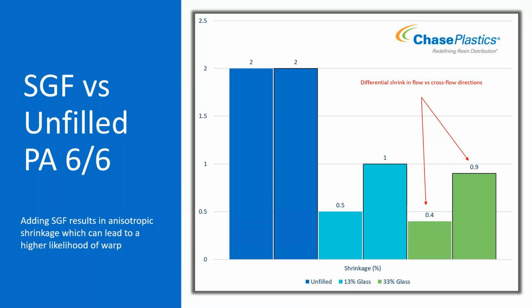You can see the 0.4 and the 0.5 - those are in your flow direction. It does not want to shrink nearly as much because of the glass getting in the way. In your cross flow direction you're looking at 1% versus 0.9%, or 10 versus 9 thou. So a big difference - you have double the shrinkage in the cross flow direction compared to the flow direction. This is non-uniform shrinkage, anisotropic shrink. That right there is what causes your material to want to warp when it's being made.